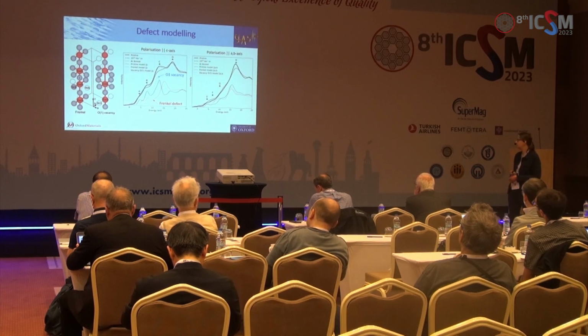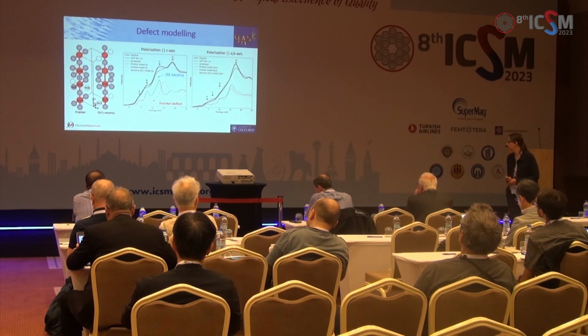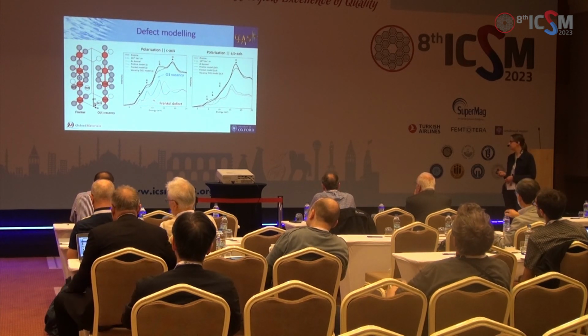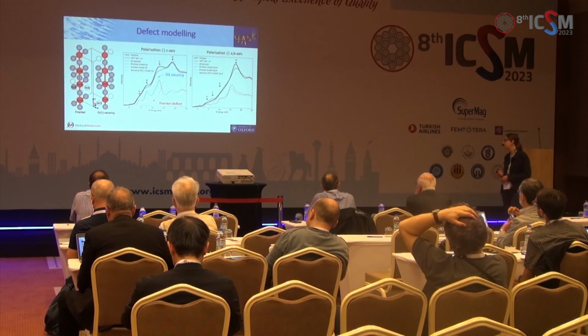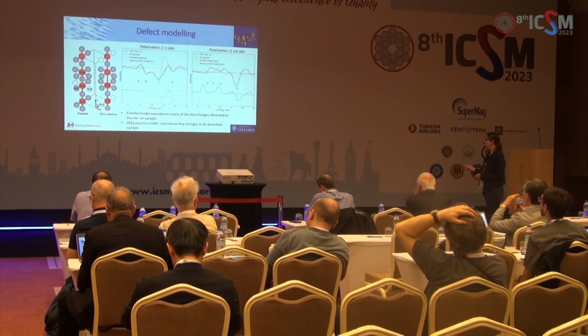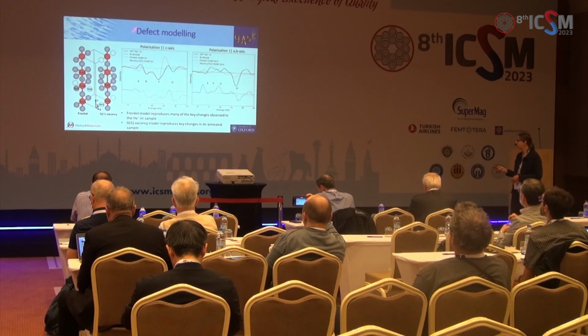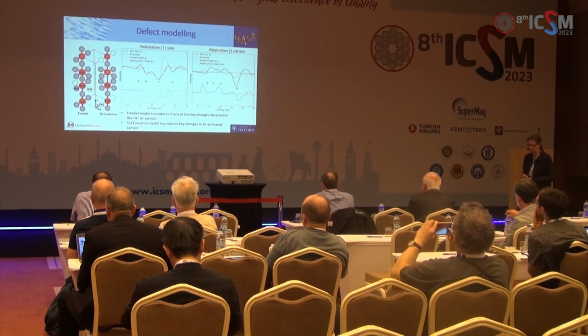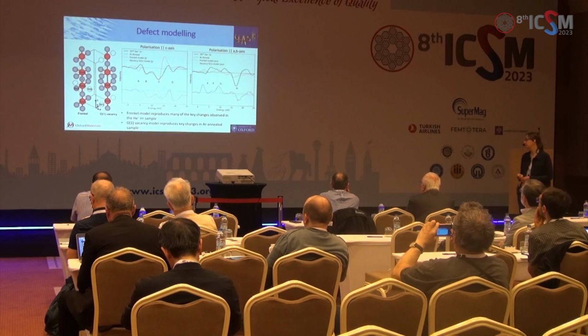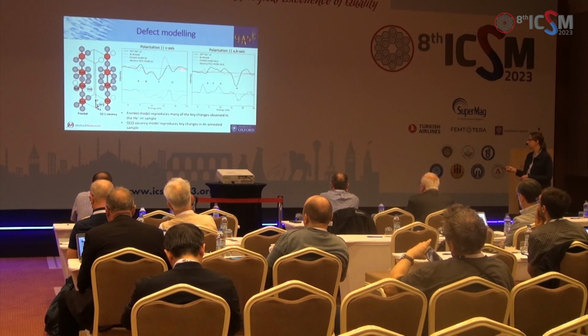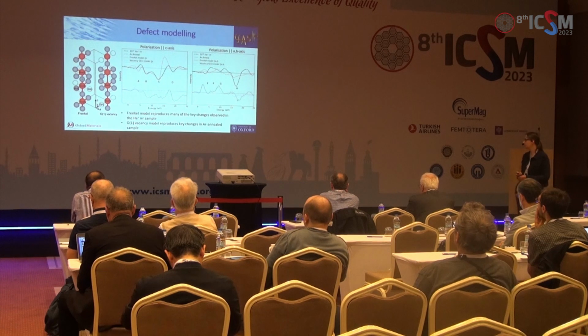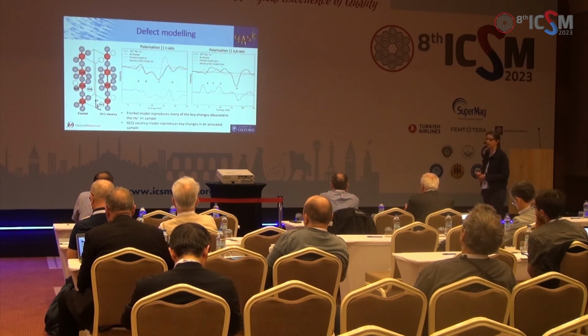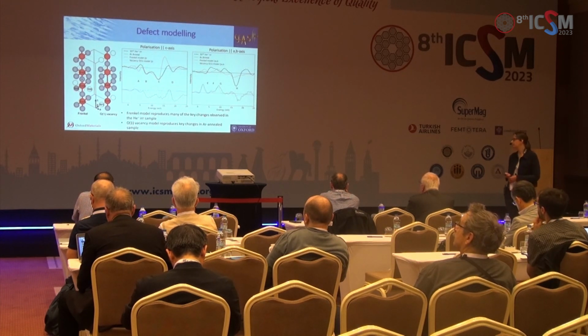Now, I don't expect you to be able to work out whether you think that we've got some Frenkel defects in there or not based on the changes with the spectra, because it's much easier to see when we do the difference spectra. So now, if I plot this a little bit differently, on the top I've got the experimental data. This is the irradiated compared to the pristine, the difference spectrum, and I've got the Frenkel model difference spectrum here as well. So you can compare the model with the experimental data. And certainly in this orientation, the shape of the changes is quite compatible with the Frenkel defect.